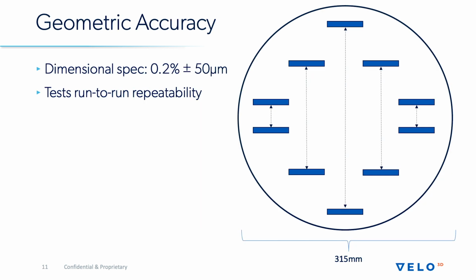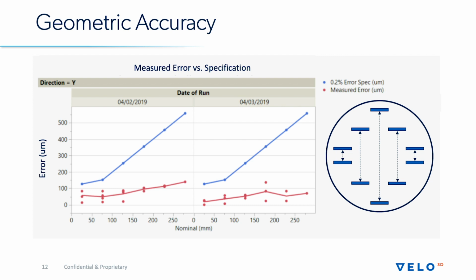To show how that works in practice, this is an example build where we basically printed different wall sections at various distances apart from each other on a build plate and tested how far apart the parts actually were printed over several runs to determine the run-to-run variability. In this case, we're targeting a dimensional accuracy spec of 0.2% plus or minus 50 microns. On the next slide, I've got the actual results that come from that particular measurement, where on the y-axis, you have the measured error in terms of the gaps between the two parts. And on the x-axis is how far apart the parts are to begin with.